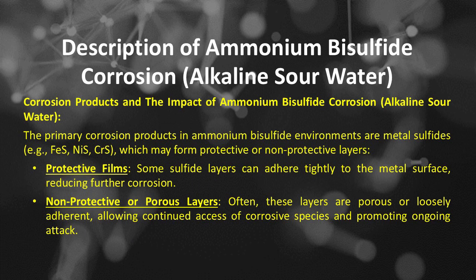Corrosion products and the impact of ammonium bisulfide corrosion or alkaline sour water. The primary corrosion products in ammonium bisulfide environments are metal sulfides, for example ferrous sulfide, nickel monosulfide, chromium monosulfide, which may form protective or non-protective layers. Protective films: some sulfide layers can adhere tightly to the metal surface, reducing further corrosion. Non-protective or porous layers: often, these layers are porous or loosely adherent, allowing continued access of corrosive species and promoting